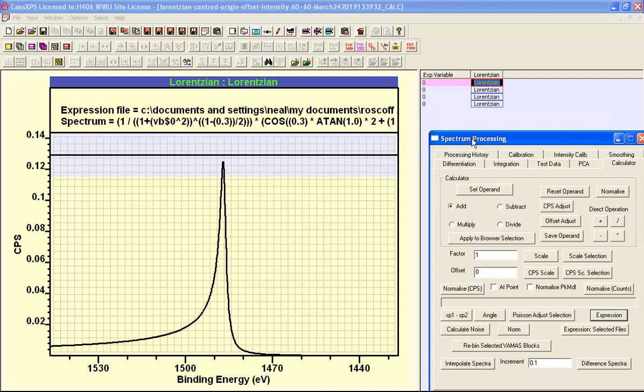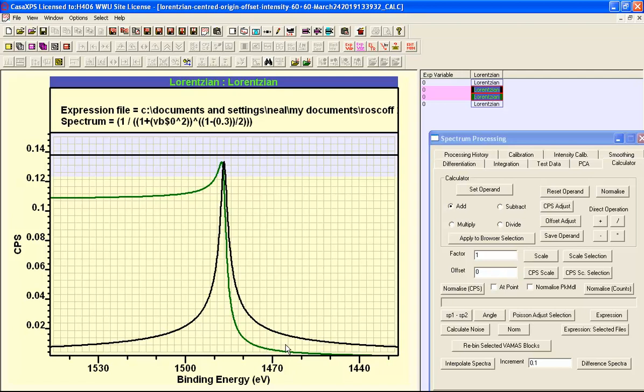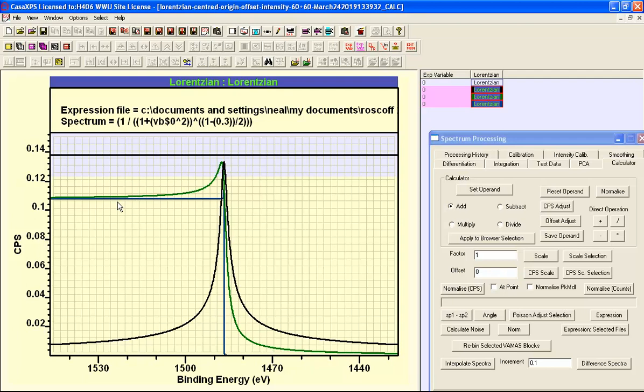After pressing the OK button, the calculation is performed. The first one was the product. This is the DS line shape for a value of alpha equal to 0.3, constructed from these two terms. This is the peak-like term that I referred to, and this is the step-like function. This step-like function will always be above a certain value.